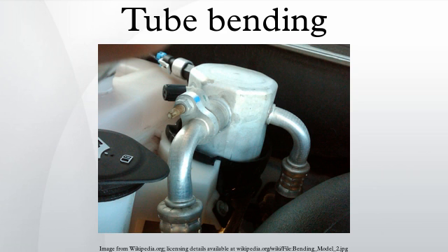One side effect of bending the workpiece is that the wall thickness changes. The wall along the inner radius of the tube becomes thicker and the outer wall becomes thinner. To reduce this, the tube may be supported internally and/or externally to preserve the cross-section. Depending on the bend angle, wall thickness, and bending process, the inside of the wall may wrinkle.